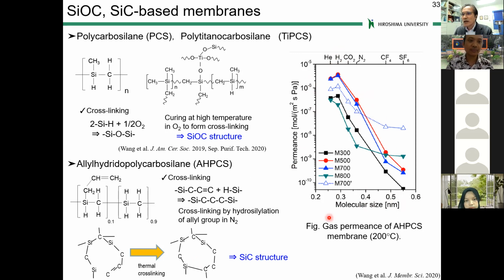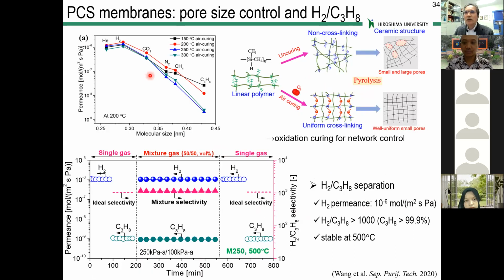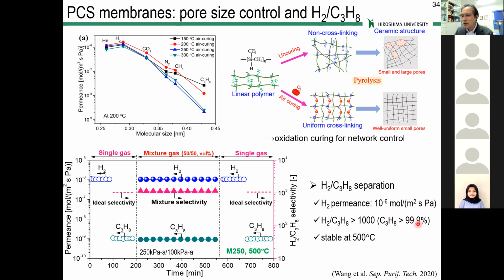over other gases. Now I'd like to briefly share with you some of the separation results of hydrogen over propane, single and mixture, using membranes of PCS, polycarbosilane type membranes, at 500 degrees C. You can see this is single and the mixture. The hydrogen permeance is higher than 10⁻⁶. Also, hydrogen over propane selectivity is higher than 1,000. So we can get a high propane purity of 99%.